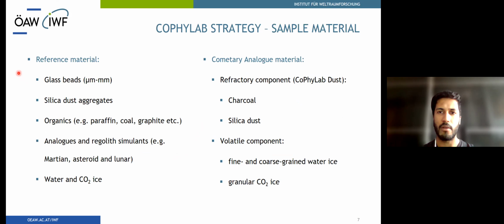Now, I mentioned simple and complex materials, but I didn't explain what they refer to. Simple materials contain only one component, which can be refractory, organic, or volatile. The purpose is to understand how mechanical, optical, and thermophysical properties depend on the size distribution, shape, and composition of a granular or bulk medium. After characterizing the reference materials through a series of S experiments, a recipe for a cometary analog material was defined that matches as many physical properties of a real comet as possible. Thereby, chemical properties were not considered. The refractory component, which consists of charcoal and silica dust, is called Cophylab dust. It can be mixed with different volatile components in varying ratios to create a complex sample.